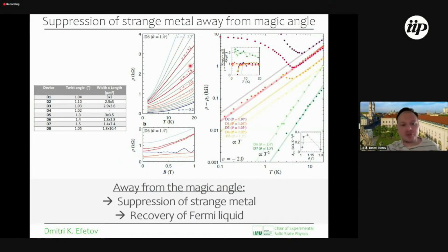So just another control experiment that we did: as I mentioned, we believe that all this physics is tied to the magic angle condition. So of course, what we can do in our experiments is tune the twist angle slightly away from magic angle. We know that if you tune the device twist angle to 1.4 degrees, this is very close to magic angle, but there the flat bands and the interactions disappear, and the 1.4 degree device behaves more or less like single layer graphene should behave. So no interactions, no quantum phases that we observe here. And indeed, we tested a number of devices which are away from the magic twist angle, and we don't see the strange metal phase.